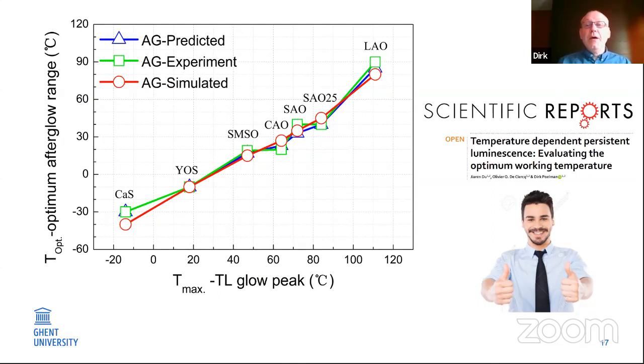Now, there turns out to be a very easy way to estimate the optimum working temperature of a persistent phosphor, because we can do this by just performing one single thermoluminescence measurement. And we look at the peak position of this thermoluminescence measurement, and we can see for these different compounds we tested. So here we have the maximum position of the thermoluminescence glow peak, and this is compared to the optimum afterglow temperature, and we also measured the afterglow, and we can find a very nice linear relationship between the position of the TL glow peak and the optimum working temperature of a persistent phosphor.